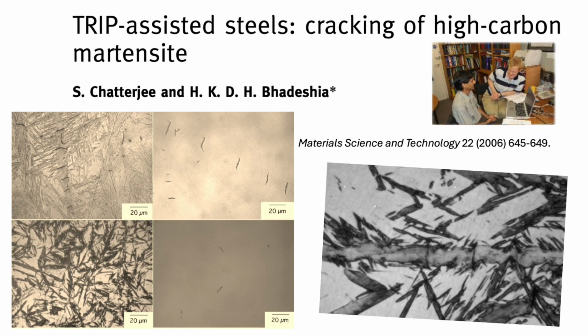That's the start. Okay. But then as the whole thing cools down towards room temperature, the core is the last part to cool and shrink. As it tries to contract, the now cold, rigid surface resists that pull. So the situation reverses. Completely. Yeah. At room temperature, the surface ends up in compression, which is actually good. It resists cracks starting. But the core ends up in tension, and that can be dangerous.